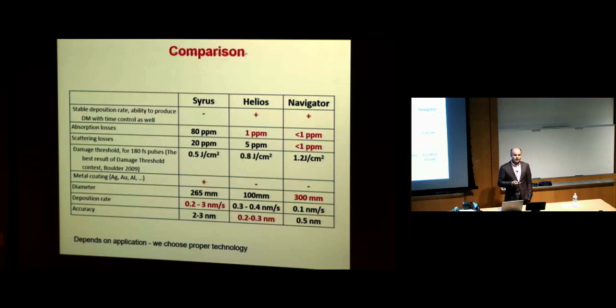Many people in some institutes say ion beam sputtering is the best technology. Other institutes say no, magnetron sputtering is the best technology. In my opinion, there is no best technology. One machine works much better for some application, another machine works much better for another application. For example, electron beam machines can produce really very large optics. When you produce optics for telescopes, it's the only machine which can be used. It also has quite a relatively high deposition rate.